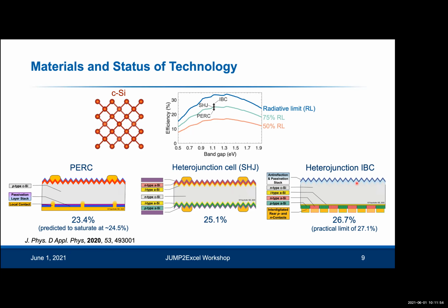A structure that was developed to overcome this limitation is called the interdigitated back contact solar cell, where you have both the P and N-type contacts at the back surface. They're interdigitated like fingers, and they extract both the electrons and holes just at the back surface. So here, you shine light in from the front surface, and in principle, you can have passivation layers that don't have such a large parasitic optical absorption. At the very least, you don't have metal fingers on the front surface, which can cause shading losses.